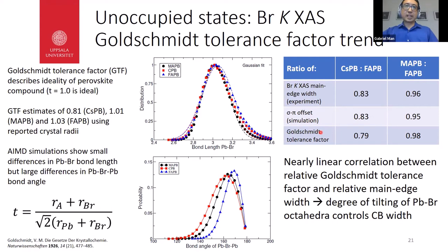To explore that a little more, we looked at our molecular dynamics simulations. This plot shows the lead-bromine bond distribution, and between the three compounds there's not a lot of difference. There are some small differences, which seem to be supported by our XAS measurements. But the biggest changes are for the tilting of the octahedra, represented as the lead-bromine-lead bond angle. Here we see that cesium lead bromide, in red, with the smallest cation size, has a lower bond angle. As the A-cation size increases, the bond angle gradually moves towards 180 degrees. So this suggests that the conduction band width is directly governed by the amount of tilting of the lead-bromine octahedra in the perovskite structure.